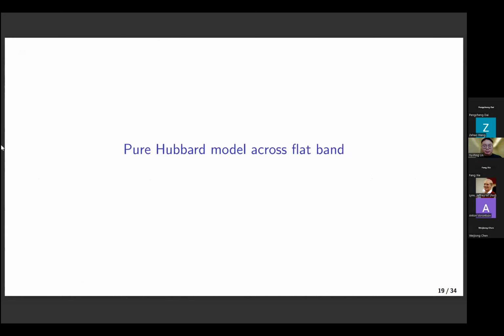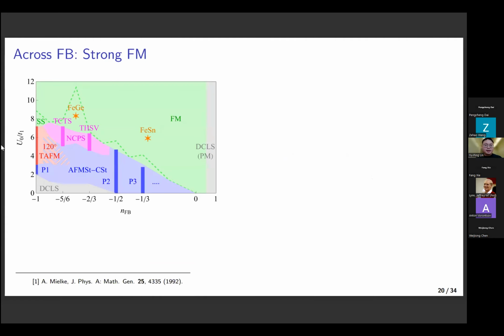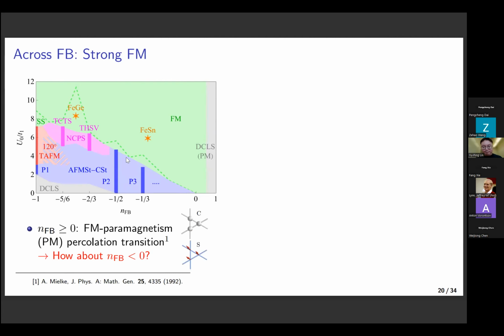First, I will tell you about the pure Hubbard model across the kagome flatband. As we have seen previously, there is very strong ferromagnetism across the flatband. If we, for example, look at the regime above the half-filled flatband, it was proposed in 1992 by Mielke that there is a ferromagnetism to paramagnetism transition from the percolation. And indeed, we also see it in the Hartree-Fock analysis. So now our question would be, what will happen if we go below the half-filled flatband? You can see that the ferromagnetism has a pattern like this. In the charge pattern, we do not see anything. And in the spin pattern, we will see a uniform ferromagnetic order here.